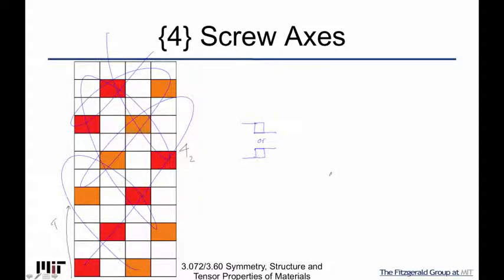So now you start to see why it was important for us to do a fourfold, because when you do the odd, you end up with spiral in one sense or the other. So for example, if we go back and think about our threefold axis, the cases where we had threefold axes, these guys had opposite sense. Now when I went to the fourfold case, I actually have, if I look at the sine curve, notice how these are opposite sense. But then I have now a symmetric one in the middle. So I've got the four one, the four three and the four two. So the even one is kind of a symmetric thing.